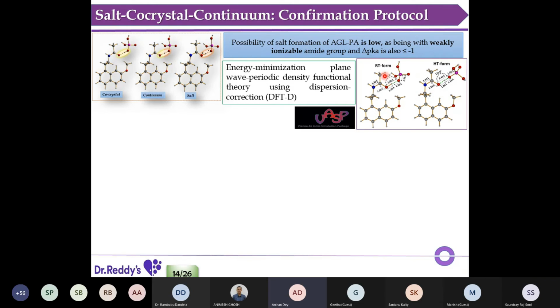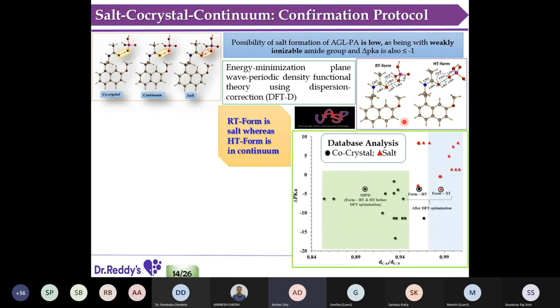And we can rely on these things because it's a DFT calculation. We can be sure about the atomic bond lengths and bond distances and all these things. On the other hand, for HT, what we saw is that this proton is mostly residing in between the amide oxygen and the phosphorus oxygen. So we did a database study. There are actually more than 20 agomelatine salts and co-crystals reported in the literature.